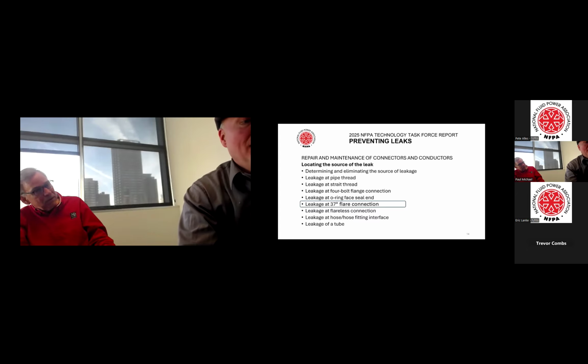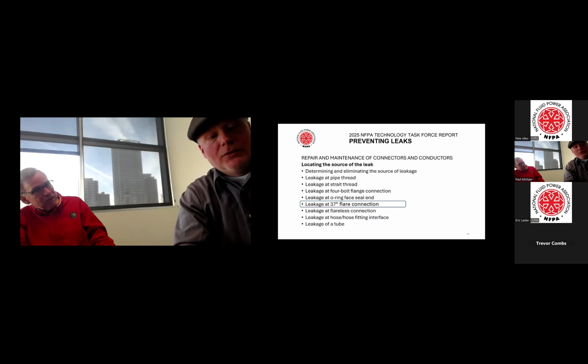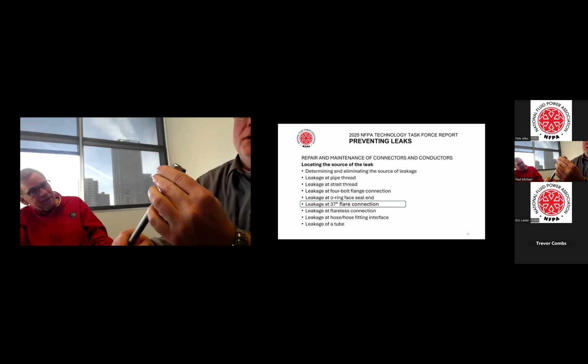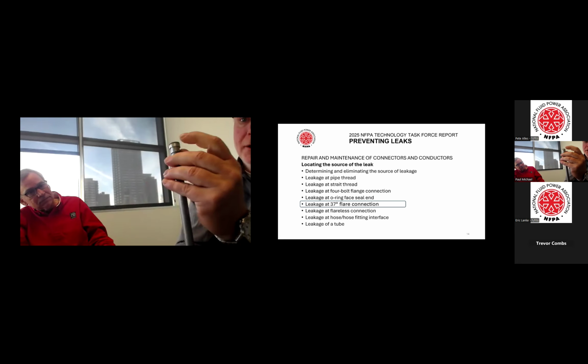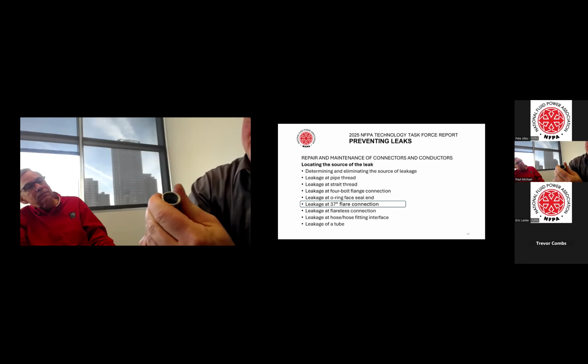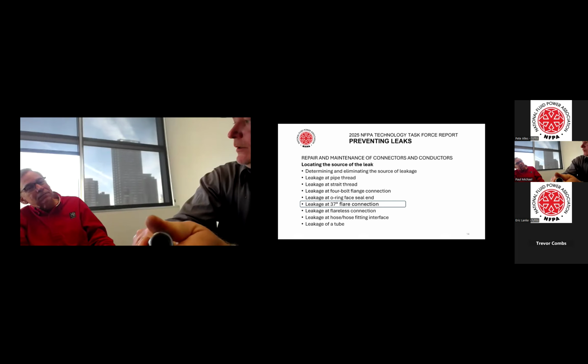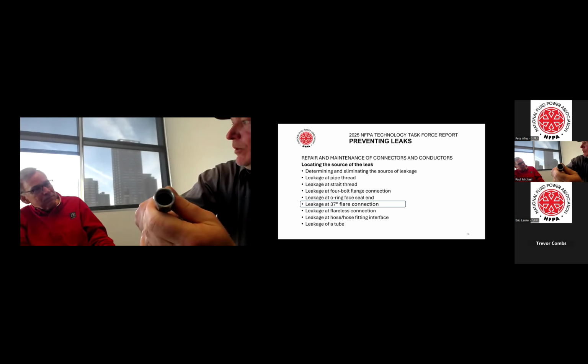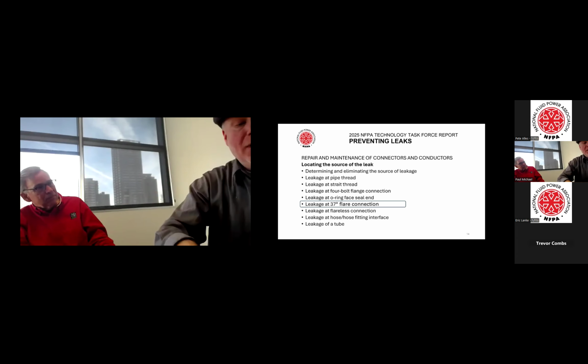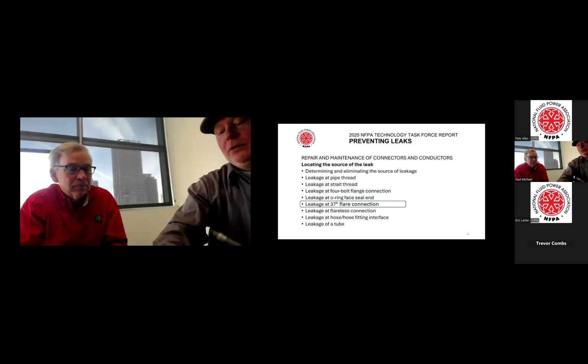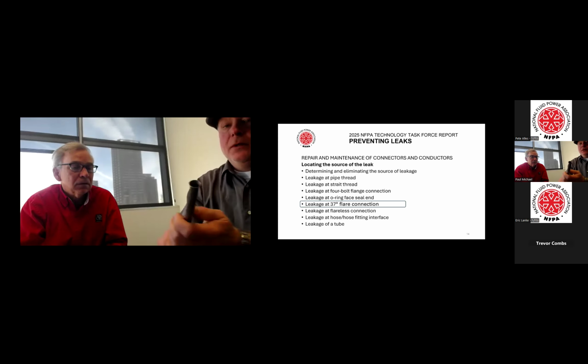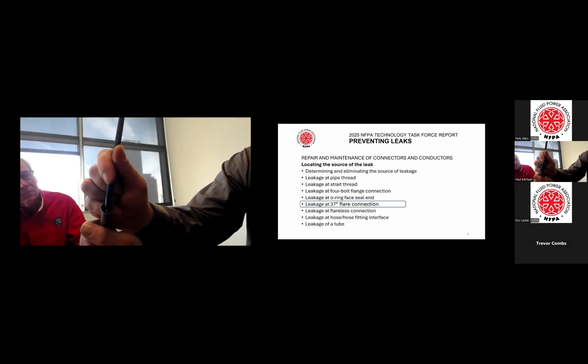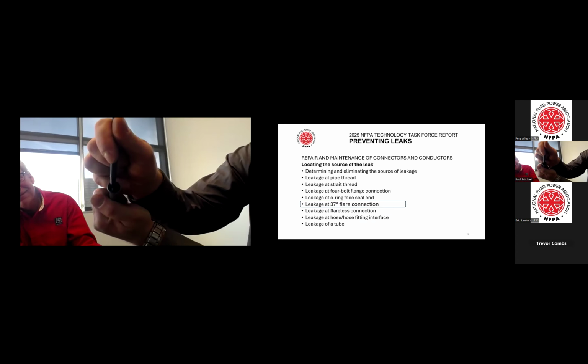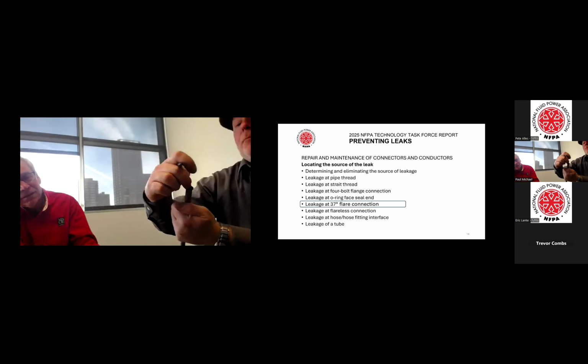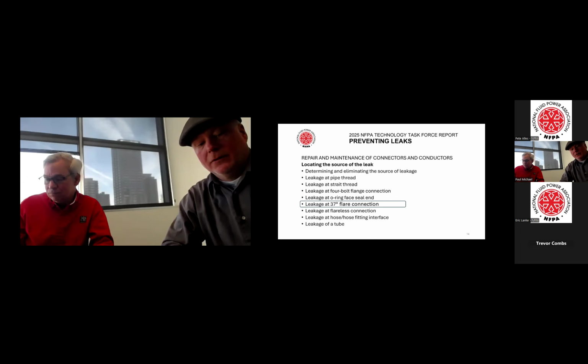Okay, so then we actually made some samples of tubing, right? This one's made correctly. This one has been over tightened to the point where you cannot spin the nut anymore. So they start twisting the tube and then they cause more damage to the tube. Most of your tubes, when they get damaged, will crack right here. Can they see that well enough on there? It cracks right there, right at the bottom of the seat. So it's very difficult to see that little tiny crack.